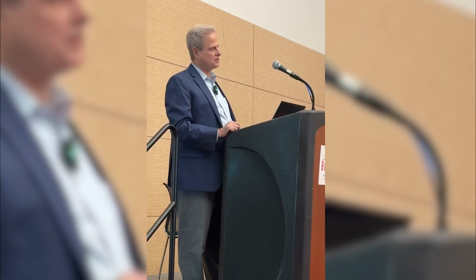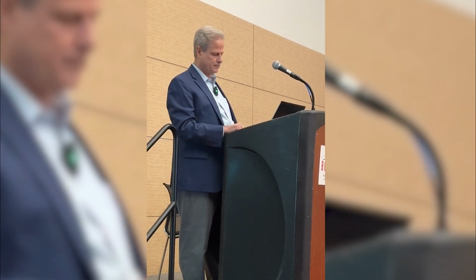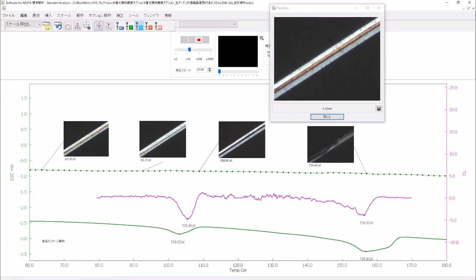Well, the problem is there's not enough sample here for DSC, okay? When we run this on DSC, we get this green curve. We get nothing. You put nothing in, you get nothing out. So putting a tiny film is the equivalent of putting nothing in your DSC. But what you get very nicely is the intensity of the light. That's in purple. That's the derivative of the intensity.